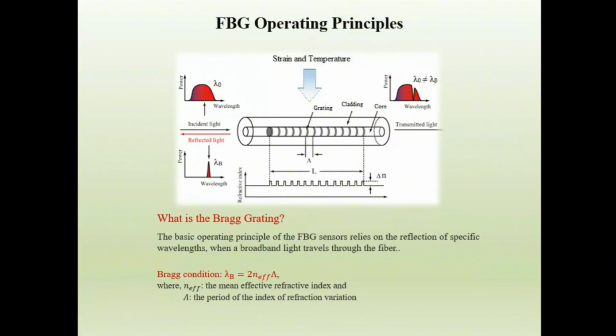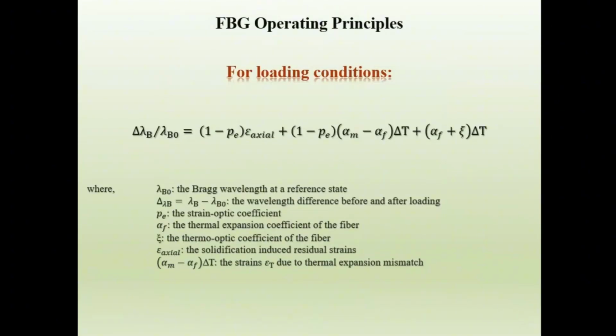Just to give you an idea, what we try to do is to utilize the basic operating principles of the fiber optic FBG sensors, which rely on the reflection of a specific wavelength when a broadband light travels through the fiber, and under axial strains, changing this spacing L that you can see here. So we get that response out of the refracted and reflected light. And by using this Bragg condition, we can proceed to a general equation that incorporates insight, starting from the reference value. This is the one that is recorded before loading, and then we can have insight either into the axial, external mechanical loading, or into the thermal loading, and we can decouple them, or we can have all of them together at the same time.